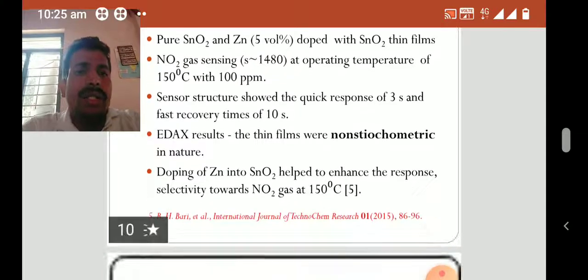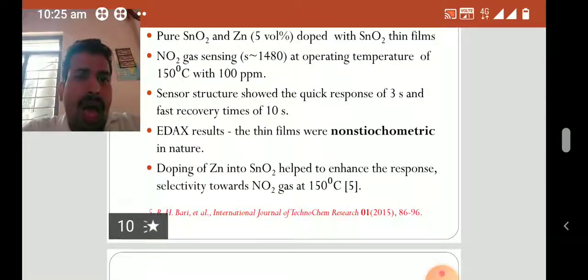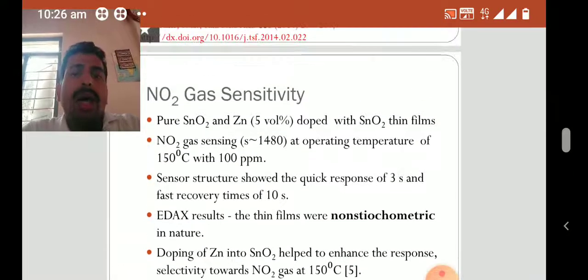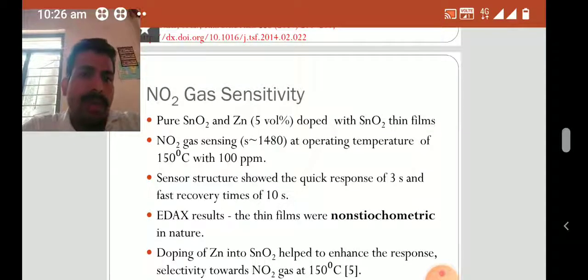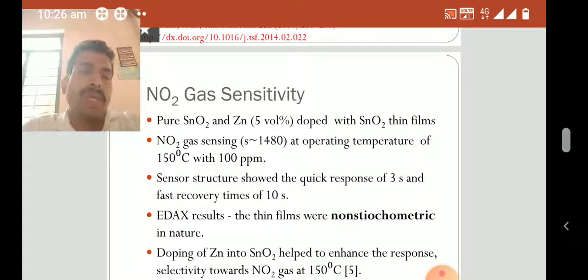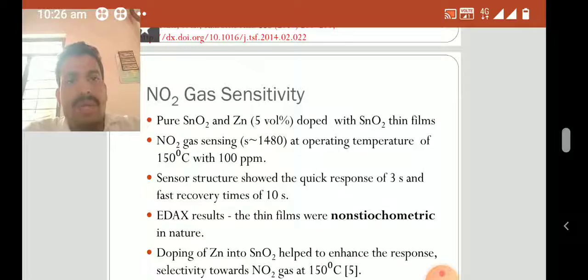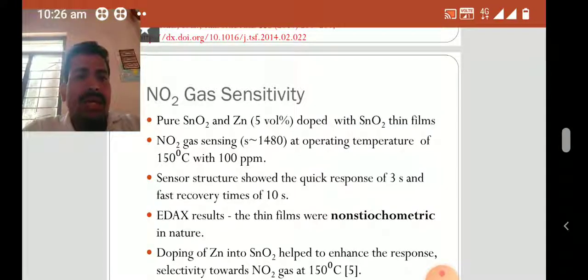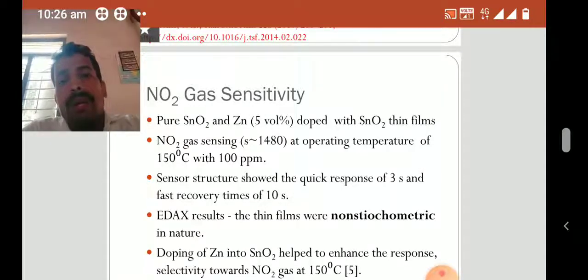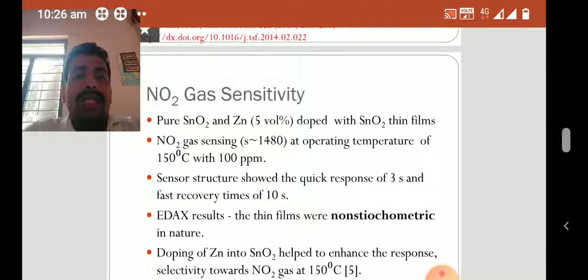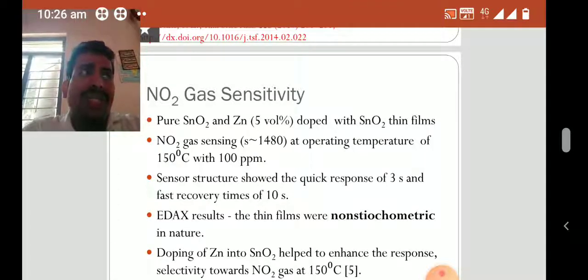And there is another study carried out by S.H. Bari on nitrogen dioxide gas sensitivity. Pure tin oxide and zinc oxide, with a percentage volume ratio of 5, doped tin oxide thin film. For nitrogen dioxide gas sensing, a sensitivity of 1480 at an operating temperature of 150 degrees Celsius with 100 ppm has occurred. The sensor structure showed a quick response of 3 seconds and fast recovery time of 10 seconds.